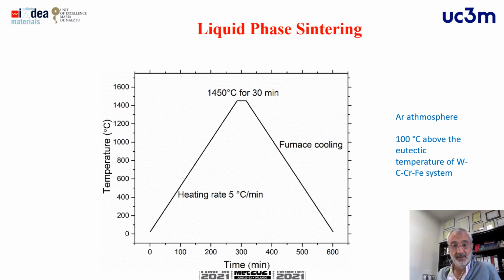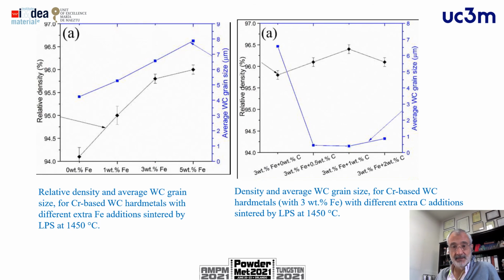We heat it up to 1450 degrees for 30 minutes and furnace cooling in argon atmosphere. We have selected this temperature because it's about 100 degrees above the eutectic temperature of the tungsten carbide chromium system. These materials reach a relative density near 96% in the case of some iron additions, but as I mentioned before, we have combined iron additions and carbon additions in order to increase the sinterability of these cemented carbides.